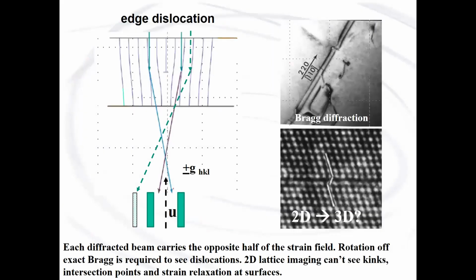The method that we use, this just shows why dislocations aren't able to be imaged by diffraction contrast, because the diffraction occurs off to the side of the dislocation core. And so we have a contrast off to the side of the core. And you can see that here. Here's the diffraction contrast of dislocations, and where that contrast lies is not actually the core of the dislocation. In lattice imaging, it's a two-dimensional image of a three-dimensional structure, so we can't see things like kinks, intersection points, or any kind of strain relaxation at surfaces.